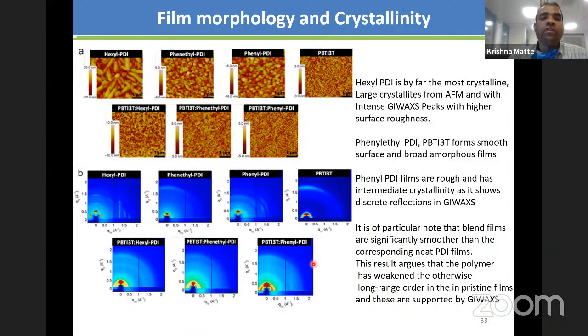The nano component of this is, as I said, when you have this donor and acceptor interface, if you mix them together and the interface is good, only then will you be able to fabricate devices of good quality. From the AFM images, we also found that if you take one of those, like Hexyl PDI, you see the crystallites are so large, but when you come to the phenyl PDI, you have an optimum amount of donor acceptor interface. The same thing has been confirmed again using GIWAXS, grazing incidence wide angle X-ray scattering, which essentially tells you about the crystallinity.